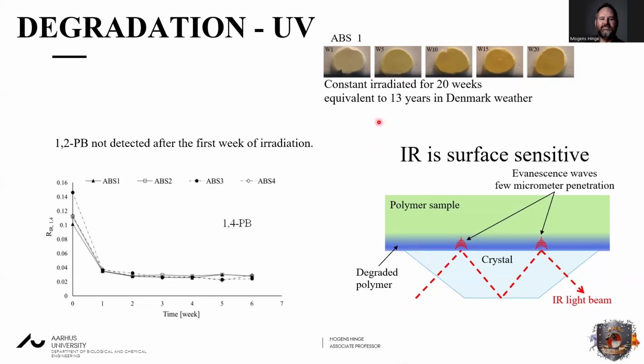But what I'm trying to say is that you irradiate on the top here. If you turn these around, then even after 20 weeks, or at least definitely after 5, the backside is not affected because this method is a line of sight method. And that basically means that we relatively fast will lose our signal, even though you have fresh and virgin material on the backside of this. Whenever the first few micrometers are broken, then you start to see a disappearing of the signal.